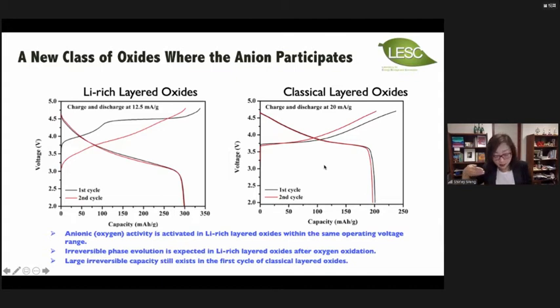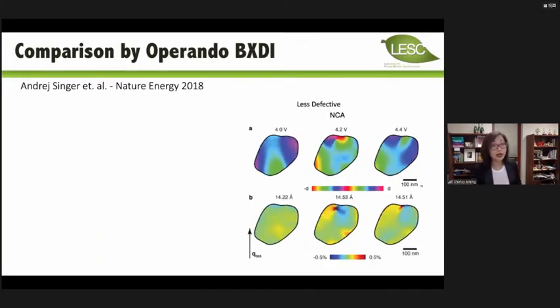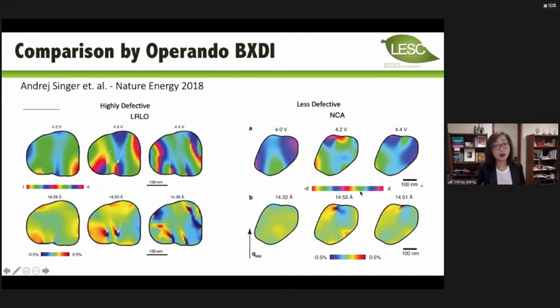But just the battery performance itself is not interesting, right? What interested the scientists is what are the new signs that enable us to store more lithium, store more energy in the matter, right? So this is where we utilize the state-of-art coherent X-ray diffraction, because the coherent X-ray diffraction can enable us to detect the strain during intercalation and to detect the defects such as dislocation, screw dislocation or edge dislocation generated during the electrochemical operation.